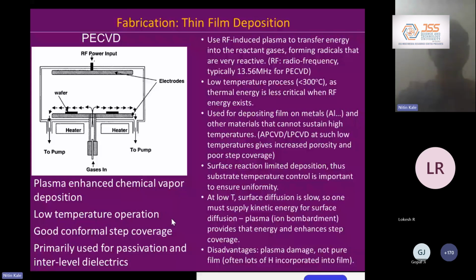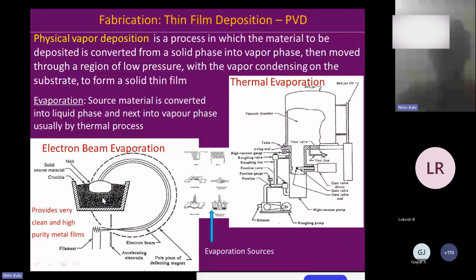You can have a thin film deposition which is in the form of physical vapors, like evaporation. So you could have either a thermal evaporator or you could have an E-beam evaporator. So what do you do? You have a vacuum chamber, you have your source material which could be gold. You have your wafers which are stuck inside your chamber, and then you heat your boat which is having the gold wire to a very, very high temperature.